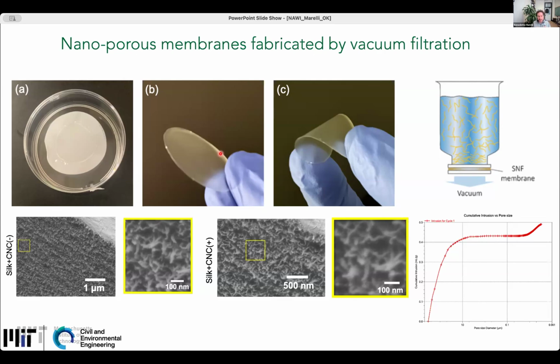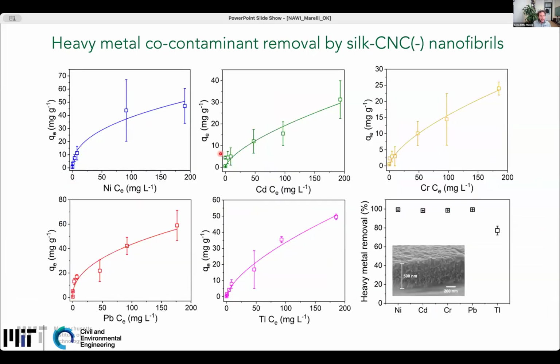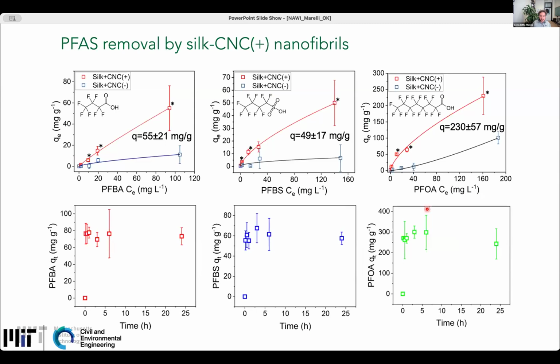They have a nanoporosity that can be engineered by changing the parameters, the knobs that regulate the self-assembly, so the size of the nanofibrils and the growth rate of the nanofibrils in water. This membrane can be used to remove heavy metals. For example, in this case, we show that we can remove nickel, cadmium, chromium, lead, and a little bit of thallium. And this is the performance that you get when it comes to heavy metal removal, which goes to very high levels.